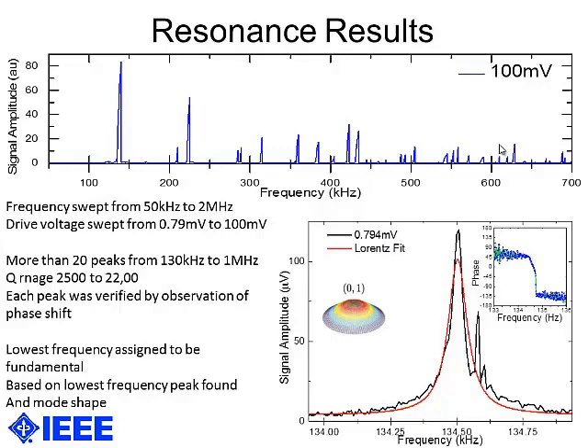We looked at more than 20 peaks ranging from the first peak found at 130 kilohertz to the 1 megahertz range, and the Q factors were found to be from 2,500 to 22,000 in this range. Each peak was verified by looking at the phase shift of the peak.